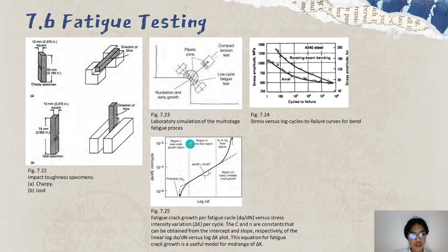In picture 7.25 is the fatigue crack growth rate per fatigue cycle, da/dN, versus stress intensity variation, delta K, per cycle. C and n are constants that can be obtained from the intercept and slope, respectively, of the linear log da/dN versus log delta K plot. This equation for fatigue crack growth rate is a useful model for the mid-range of delta K.